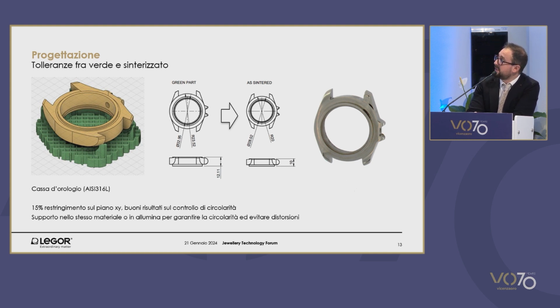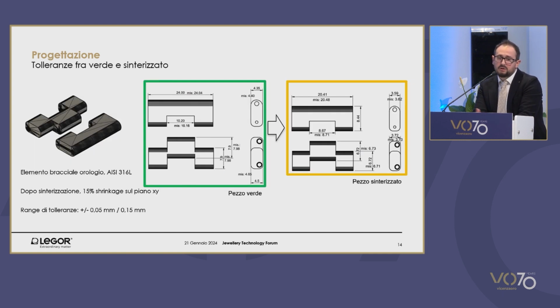On your left in green, you can see another support. This is for a watch box. This is AISI 316L. And in this way, we can guarantee excellent tolerance in terms of the circular shape of the item. The very same item produced without the support showed a distortion with a tapering between the base and the upper part of the object. This is another example. Here you can see the different tolerances. We're talking about items with a base size less than 8 by 8 centimeters and 7 centimeters in height. Possible tolerance range goes from 0.05 to 0.15 millimeters, depending on the geometry of the item and depending on all the other aspects.